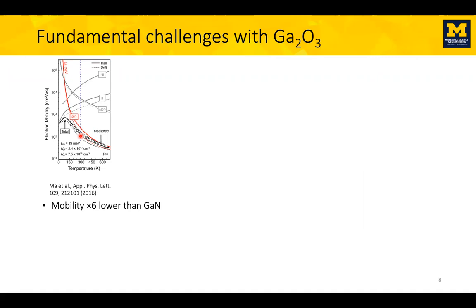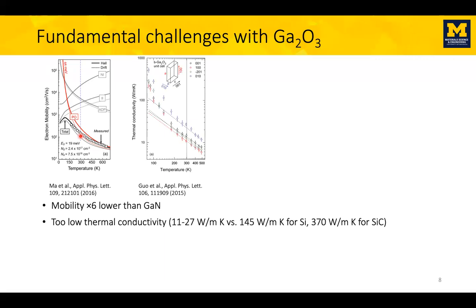So that means that the efficiency at which electricity flows through the material is not the same. It's 6 times more resistive, you produce 6 times more heat. The problem with the heat is that not only do you produce more heat, but it becomes harder to extract. The reason is the thermal conductivity of this material.